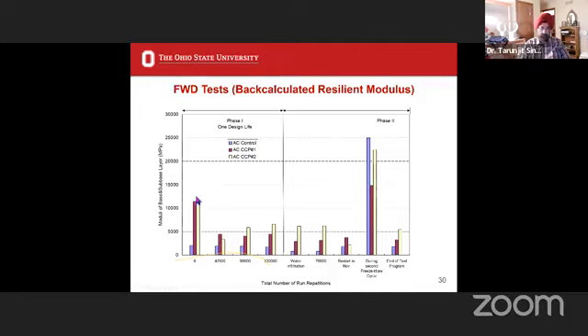using FWD tests. As you can see here, this is the control section, the asphalt control section. We are looking at the resilient modulus of the base and the sub-base, that's what we are interested in. And you can see they were much higher. As we went along, there was a slight degradation of the resilient modulus in the control section. In the CCP sections, we saw a much more significant decline, but still it was 2 to 3 times that of the control sections at the end of 20 years of cycling.